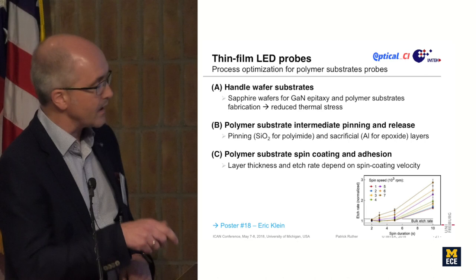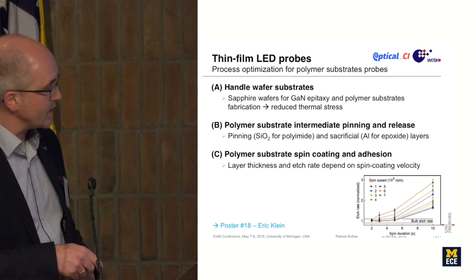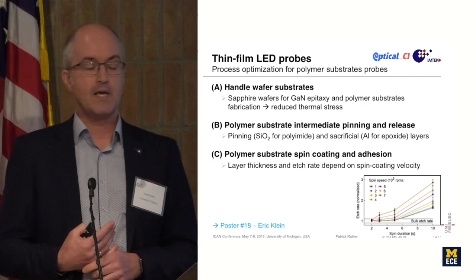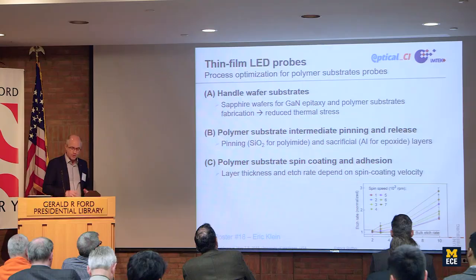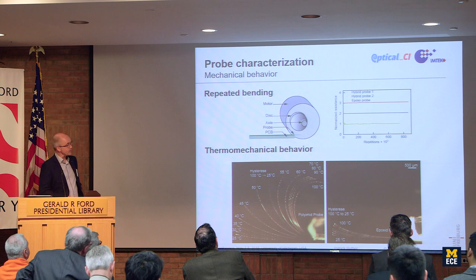And last but not least, this was a bit tricky, and Eric invested a lot of time in that, is how can we spin coat a two-component epoxy, not separating the components. So a couple of tricks and looking at etch rates as a function of spinning speed. Now as a result, we obtain probes that are mechanically robust.